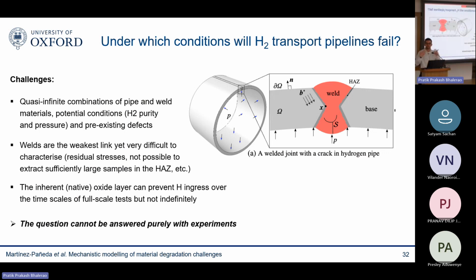And of course, as an engineer, you also have a quasi-infinite combination of hydrogen conditions. You can play with the hydrogen purity, with the hydrogen pressure. So it's very difficult to test this gigantic amount of conditions. The other problem is that where these pipelines are going to fail are the welds. We know that the welds are the weakest link, but welds are very difficult to characterize in the lab because you have residual stresses, because the weakest part of the weld is this kind of heat-affected zone that you see there. That is basically a very small region where it's difficult to extract samples that are large enough to do proper testing in your lab.